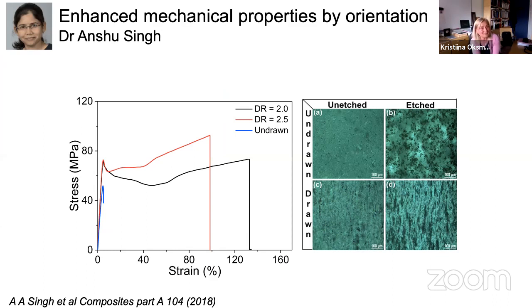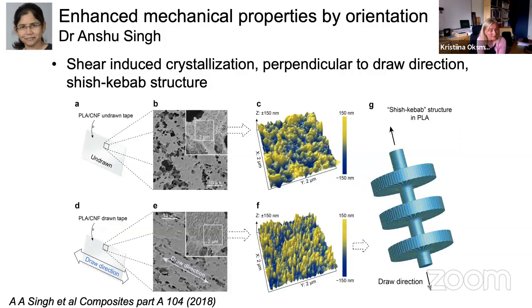So we continued with the same material. We were interested to see if we can improve the mechanical properties of that plasticized composite by making solid state drawing. And as you can see in this image, we could improve the modulus a little bit, but strength and especially the elongation to break, with the 2 and 2.5 draw ratio. And this polarized optical microscopy image here also shows that we have some orientation in the structure.